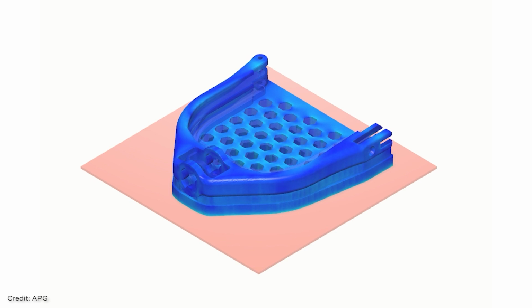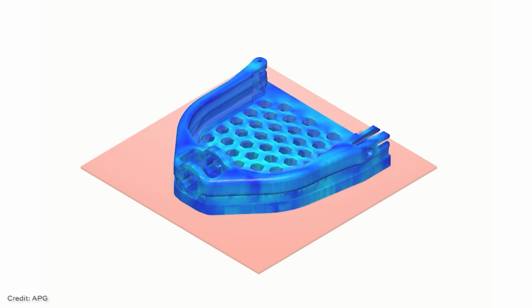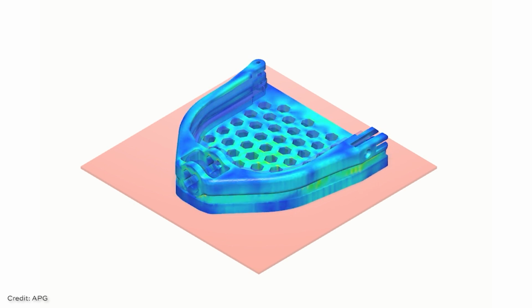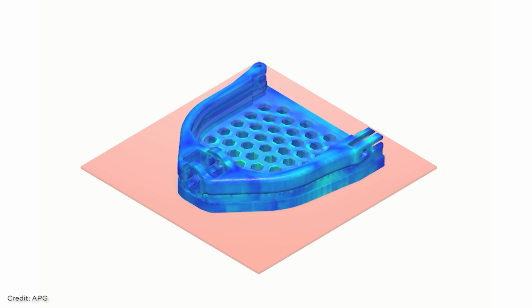Joe talked about sintering as a necessary part of the binder jetting process, necessary to metal injection molding too. In binder jetting, the 3D printed part is bound together in a green state initially, and then it's completed through sintering in a furnace. And in that furnace, crazy things can happen, do happen. There is shrinkage, for example, but that shrinkage is repeatable. There's the potential for the part to distort at those high temperatures, but the distortion is predictable and controllable. And this is really a big part of the expertise that APG brings. Very familiar with sintering from other sinter-based processes that the company has been doing for quite a while.